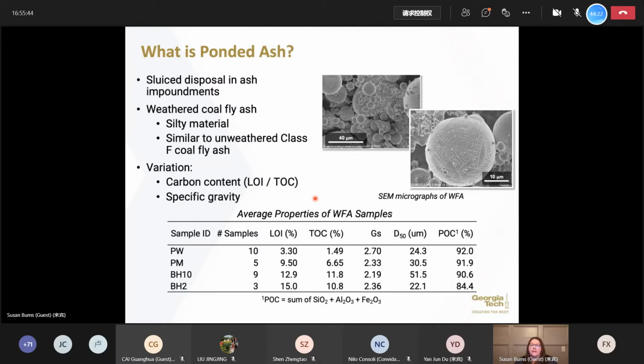There is variation in the carbon content, so that means a measure of the loss on ignition or the total organic carbon, as well as the specific gravity. But what you can see here is that we've got loss on ignition for some of the ponded ashes that we've tested that have varied from as low as about 3% up to as high as 15%. So that's a pretty big range. And that is challenging for a concrete producer because we need consistency in the incoming product.